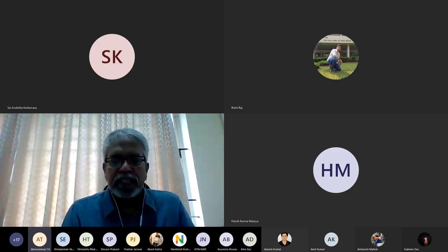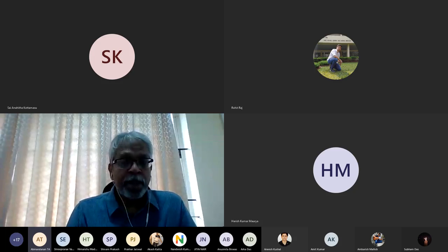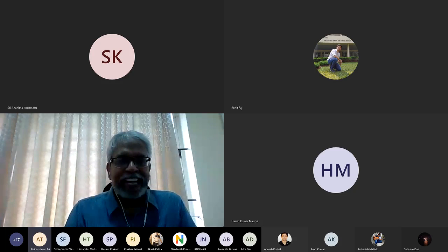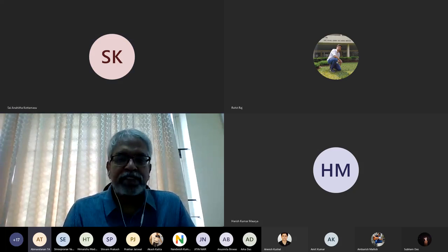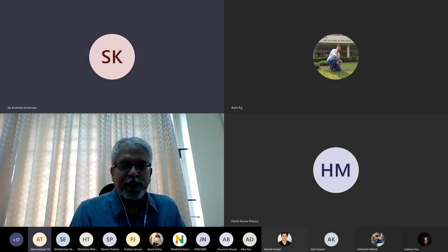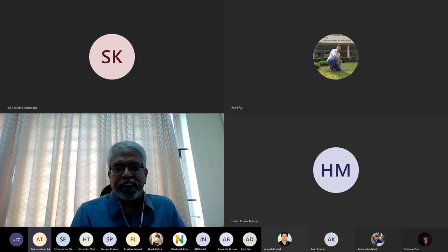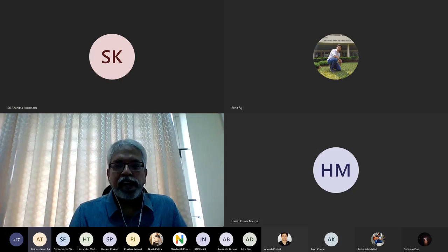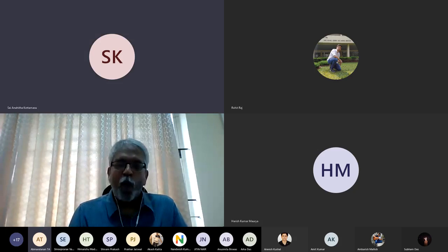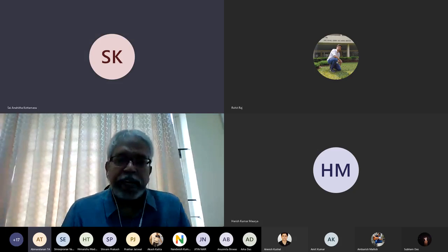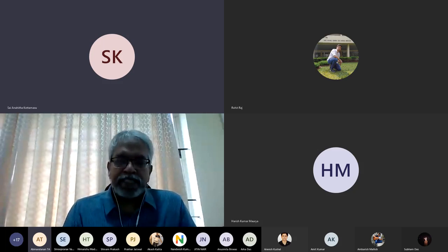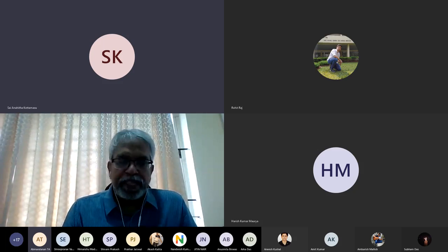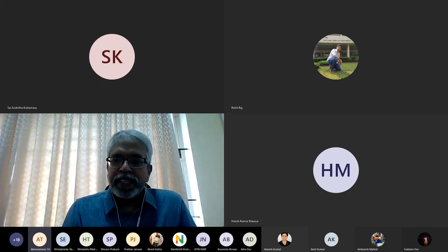So what would you call such a lattice? It would be tetragonal, right? Okay, tetragonal. But if you look at the tetragonal list, still there is no such thing as a base-centered tetragonal. But you could connect the end-centered part to the corners, so that half the base diagonal is covered. Then what happens? What does it become? Primitive tetragonal cell. Primitive tetragonal. Yeah, that's great.